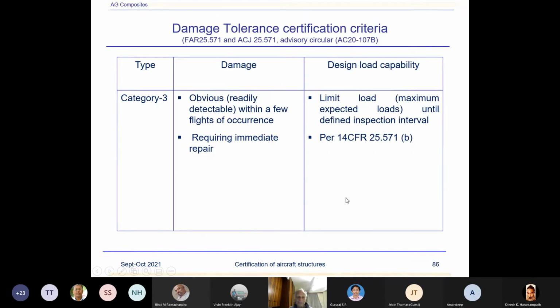The next one. So this is obviously detectable damages within a few flights of occurrence, requiring immediate repair, because that's a requirement. Once it's detected, the aircraft is not allowed to fly until the damage is repaired and returned to the ultimate load carrying capability. That's another thing. When you repair the damage, the strength after the repair must be ultimate load carrying capability. There is no reduction in that load carrying capability definition. Repair must be as per the new structure capability.